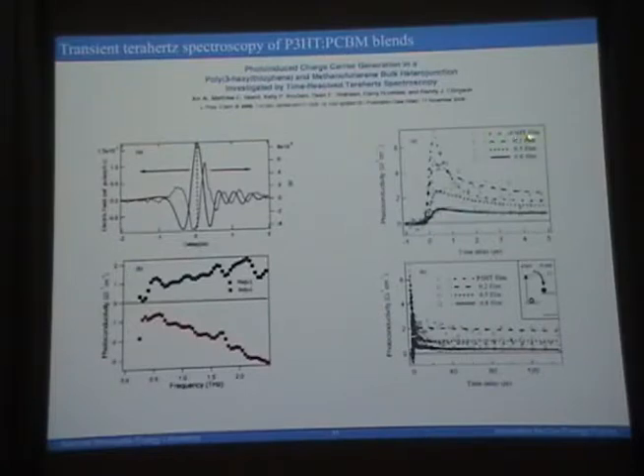So if you look at the P3HT film, just this one here, here's the absorption of terahertz. This is, shall we say, looking at mobile carriers detected by one terahertz radiation. It's a 50-50 blend. It's like a factor of two different. Isn't that surprising? So you look on an ultra-fast timescale, and the ultra-fast timescale says you've got 50% PCBM in your system, and your signal goes up by a factor of two. That seems a bit small, okay?